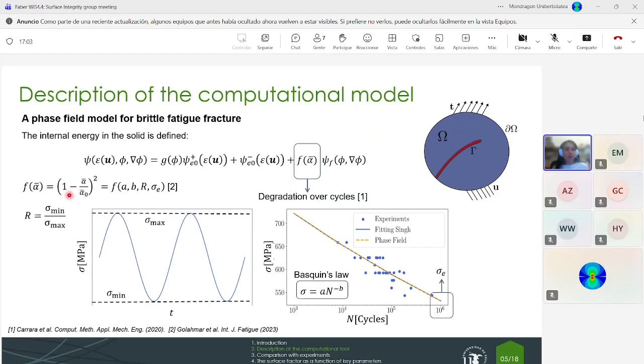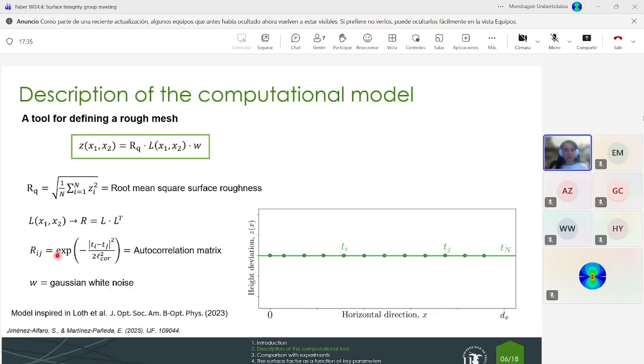You can see that this function depends on different parameters, and they are basically the parameters of the Basquin law, the stress ratio, that is the ratio between the minimum stress and the maximum stress in the cycle, and also this endurance limit. This endurance limit can be included in the model just to say to the phase field variable, do not grow if we have a stress level that is lower than the endurance limit, just to consider this infinite life, or we can just omit it and not consider that we have this infinite life, as in other materials. So now we had two different techniques.